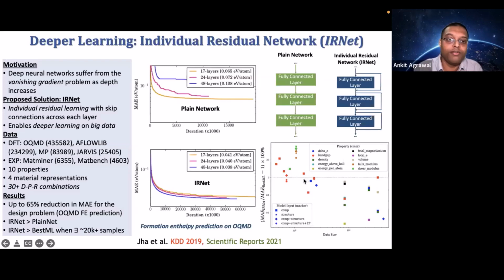But around this point, which is around 20,000 samples, we can take advantage of this deeper learning idea and make models with up to 48 or even more layers, and get up to 40-50% improvement in our model error. So this IRNet was always better than PlainNet, and better than best ML when we had more data points. So this is kind of the threshold in general for this work. And there are more details in this Scientific Reports article from last year.